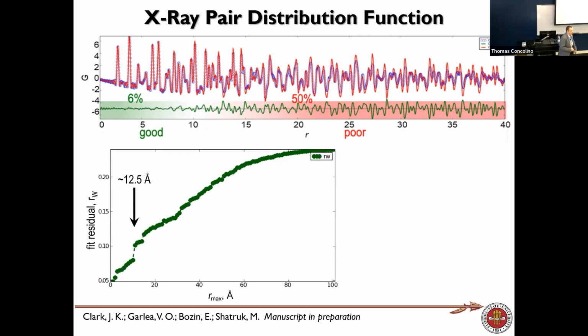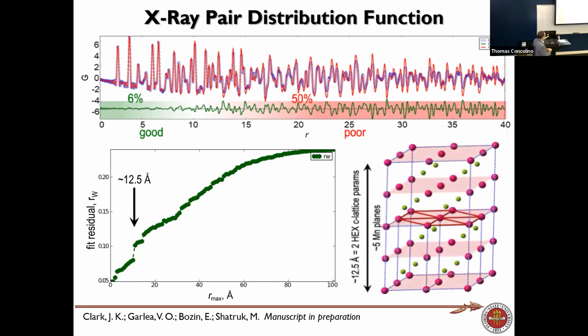and then it starts getting much worse. Okay, so our hypothesis here is that we have this kind of structural reconstruction, where our cubic phase converts to a hexagonal phase and propagates to some kind of interface. This gives us some sort of characteristic domain size measure for this transformation. So you see it moving with this characteristic domain size of five atomic planes in a hexagonal structure. So it just keeps propagating through the crystallites.